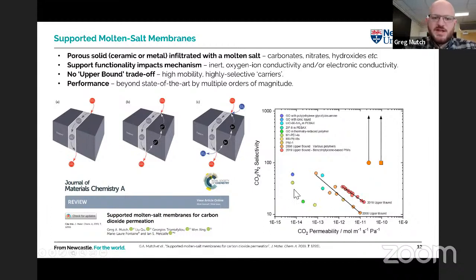But the point I would really want to stress, and the reason that I work on these membranes and that I'm interested in them, is that in this plot here, we see permeability, so how permeable the membrane is for CO2, versus selectivity. And if you look at these diagonal lines, the 2008 upper bound and the 2019 upper bound, you see that there's a trade-off in this behavior. So if you have a high permeability membrane, typically it has lower selectivity. And conversely, if you have a high selectivity membrane, typically it has lower permeability. This is a fundamental trade-off in almost all classes of membrane. It's not a trade-off in a supported molten salt membrane.